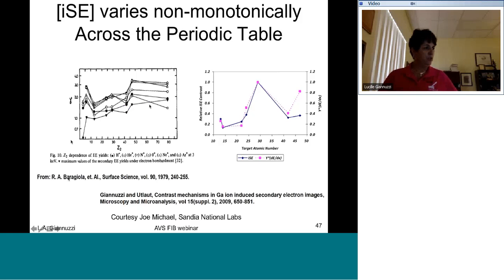So this is some work that's in the literature, and this is some work that I did early on, and it seems to follow this complex relationship both between the sputter yield and the stopping power as well. So also, just to kind of finish this up, it's extremely complex. It's not fully known why these differences occur, other than there are definitely periodic effects or filling effects across the periodic table, which vary in a very complex manner between sputter yield and stopping power.